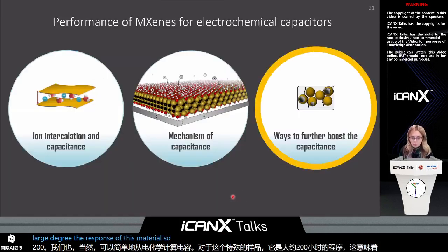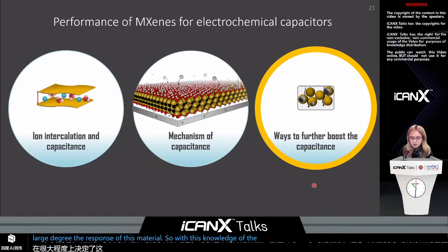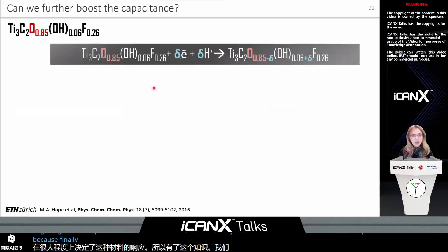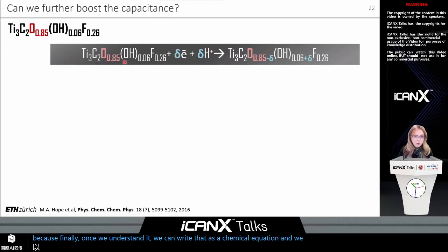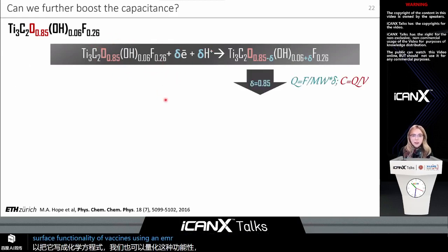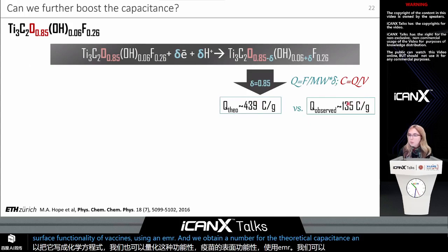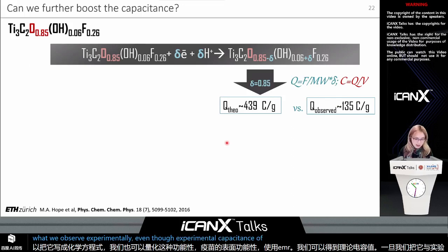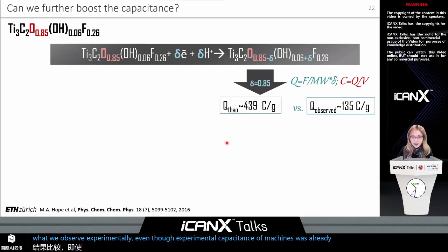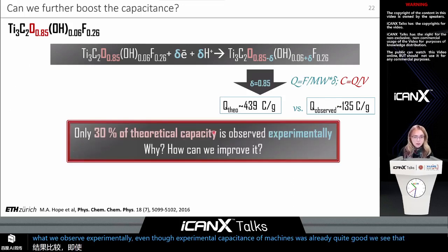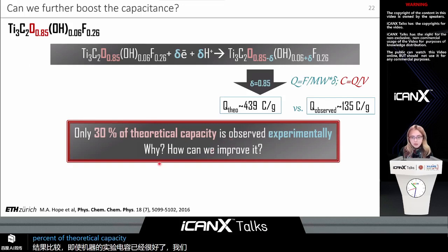So with this knowledge of the mechanism, we can look at the theoretical capabilities of this material, because finally, once we understand it, we can write the electrochemical equation, and we can also quantify these functionalities, the surface functionalities of MXenes using NMR. And we obtain a number for the theoretical capacitance. And once we compare it with what we observe experimentally, even though experimental capacitance of MXenes was already quite good, we see that only 30% of theoretical capacity is observed experimentally.